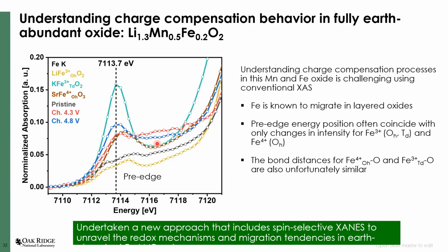So one of the fundamental things we want to understand is, when lithium is put in or taken out of these oxides, what is charge compensating and how is the charge compensation process taking place? There is a variety of methods one can use to look at charge compensation. Perhaps one of the most often used is X-ray absorption, because the absorption at the transition metal, the so-called pre-edge, can give information about oxidation state and symmetry. But it turns out in the case of iron, the pre-edge position coincides for a variety of environments. And whether the iron is tetrahedral or octahedral, the bond distances tend to be very similar. So you cannot use either the pre-edge or a measure of the local bond distance as a fingerprint of